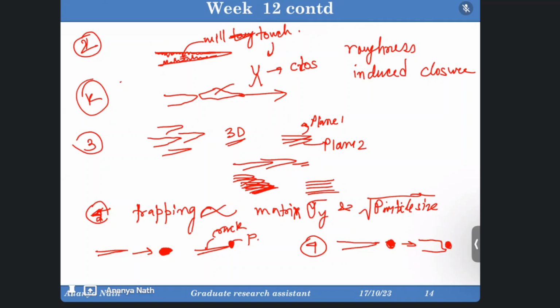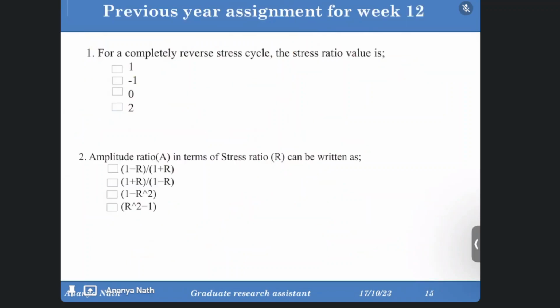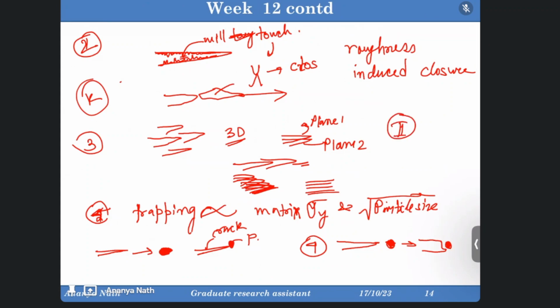So similarly, if you're discussing the mid-range growth, that is the stage 2 growth, there the cyclic loading can lead to work hardening. So there can be dynamic fracture, where the fracture takes place at the time of loading, or there can be a static mode of fracture where the particles are fractured and you'll get a sudden fracture in the whole material, or it can be matrix void nucleation, then void growth, then coalescence of the voids and it's getting filled. So both things can take place. Then the next topic is effect of microstructure.